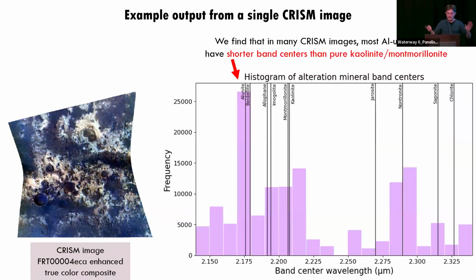We can also look at this data in a different way. Here I'm showing a histogram, still band center wavelength, but now the y-axis is frequency. And we can see, at least in this CRISM image, that a lot of the pixels in the aluminum unit actually have band centers that are slightly shorter than you'd expect for like a pure montmorillonite or kaolinite. There are still some pixels that are consistent there, but many actually cluster seemingly around like halloysite or something like that. And that's an interesting thing we want to follow up with. We see it in a lot of CRISM images.